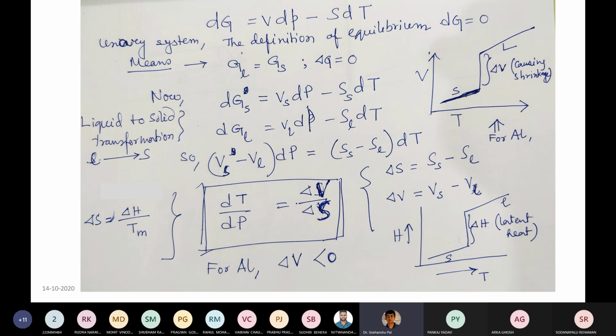So change in volume, and that can be determined as the melting point, or the temperature at which it is going to solidify. And since it's a pure material, the temperature should be a single point temperature. For pure material, the boiling point and melting point are single temperatures. Okay, and for an alloy, it can be a range of temperature based on the composition of that alloy.